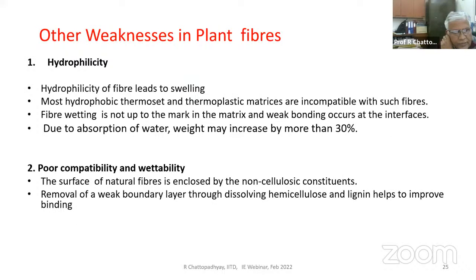The other weakness is hydrophilicity. Hydrophilicity of the fiber leads to swelling. And therefore, it may give problems especially in some products where swelling can change the properties. Most hydrophobic thermoset and thermoplastic matrices are incompatible with such fibers. Due to absorption of water, weight may increase by more than 30%. So these are some of the problems that you face, this fiber being hydrophilic. But there could be advantages also in being hydrophilic in some other applications. So we should see that the same property could be advantageous in some products and disadvantageous in other products. Poor compatibility and wettability.